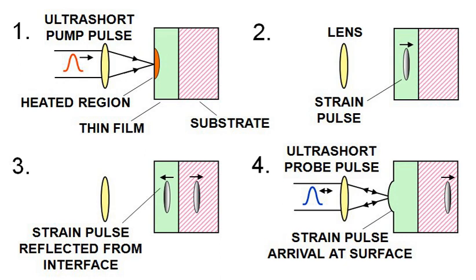The strain pulse forms a pancake-like region of longitudinal strain that propagates directly into the solid away from the surface. For small spot sizes approaching the optical diffraction limit, for example d approximately 1 micrometer, it may be necessary to consider the three-dimensional nature of the problem. In this case acoustic mode conversion at surfaces and interfaces and acoustic diffraction play an important role, resulting in the involvement of both shear and longitudinal polarizations. The strain pulse separates into different polarization components and spreads out laterally for distances greater than d micrometers as it propagates down into the sample, resulting in a more complicated three-dimensional strain distribution.